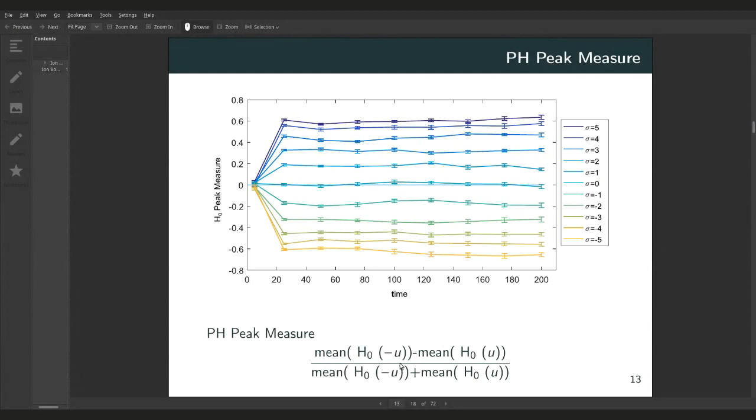Something else you can notice from this plot is that you have this big shift in early time. And what this is telling you is that from approximately time 5 to 25, we're going from the linear regime, where the linear effects are really dominating the pattern formation, to the nonlinear regime. And so we can really see where this shift takes place from this statistic. That wasn't expected, but it's a nice side benefit of being able to see that here. So we can understand when the pattern really emerges.